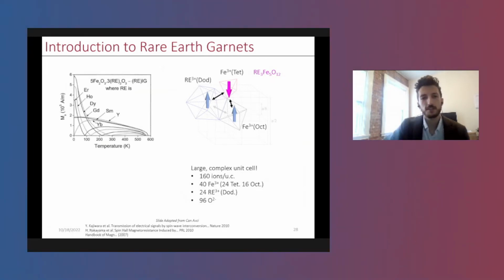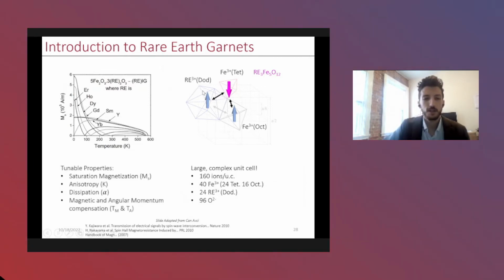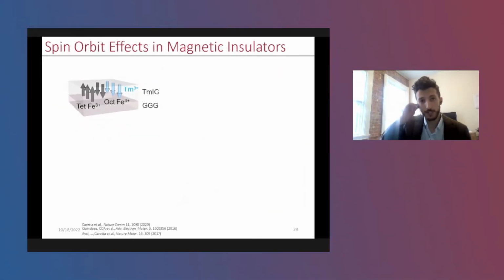Now the beauty of these systems is just by choosing this rare earth ion, you can tune a number of different materials parameters, such as the anisotropy. You can even control the dissipation in these materials, and of course their magnetization and angular momentum as a function of temperature. And here up above, I'm just plotting an example of that, the magnetization as a function of temperature for a variety of different rare earth iron garnets. We can control the compensation, all while retaining very high Curie temperatures in these material systems. So these systems have been around for decades, even in thin film form. They've been around, I think, since at least the 60s, so that's over 50 years.